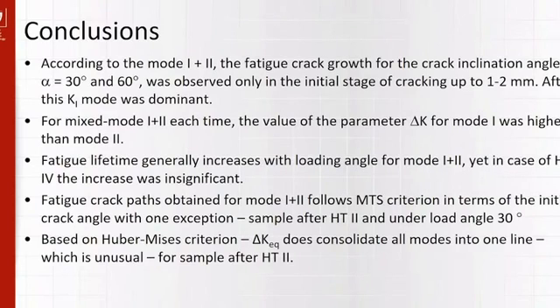For the mixed mode 1+2, each time the value of the parameter delta K for mode 1 was higher than for mode 2. Fatigue lifetime generally increases with loading angle. Fatigue cracks obtained for mode 1+2 follow the MTS criterion with one exception, which is the sample after HT2 under load angle 30 degrees. I can also say that based on the Huber-Mises criterion, delta K equivalent does consolidate all modes into one line, which is unusual.